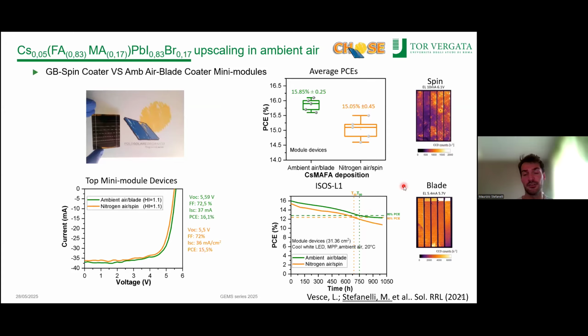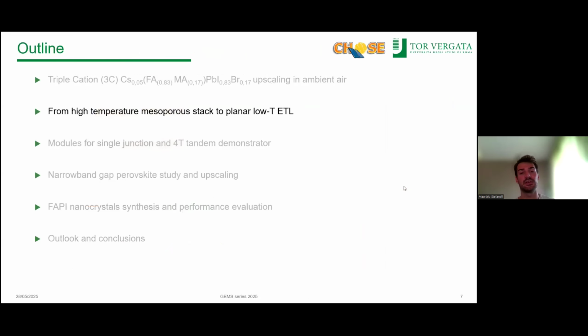Okay, once we got an efficiency comparable with our nitrogen spin-coated device, we moved to the optimization of the ETL. In this case, we need a low temperature ETL, because to get larger and larger substrates and larger modules, you want to avoid a high temperature process like compact TiO2 with spray pyrolysis and calcination of TiO2 at 500 degrees. That is not only a disfavored process for industry because of the energetic cost, but the high temperature can also crack your substrate and you have to redo everything from the start.